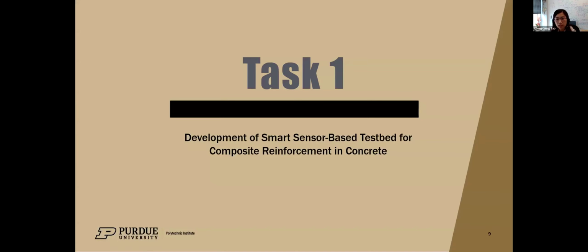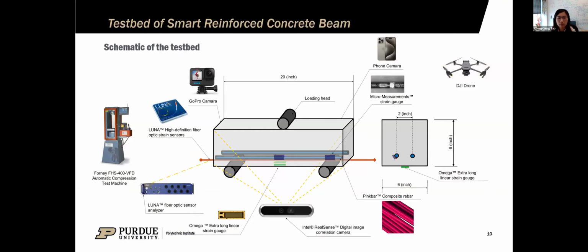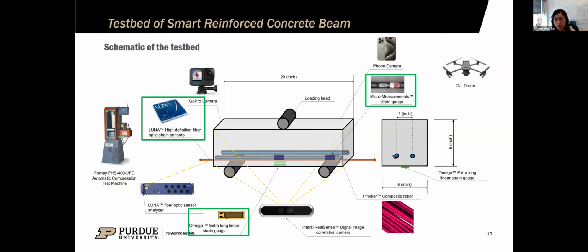So the first task is the development of the smart sensor-based test bed. So here is the schematic of the test bed of the smart reinforced concrete beam. We applied 3 different smart sensors, including the embedded fiber optic sensor for the composite rebar. And we have the micro measurement strain gauge attached on the rebar to measure the point strains as well. And we also have the extra long linear strain gauge for concrete to measure the strain of the concrete.